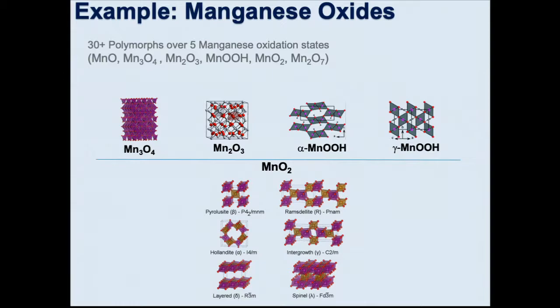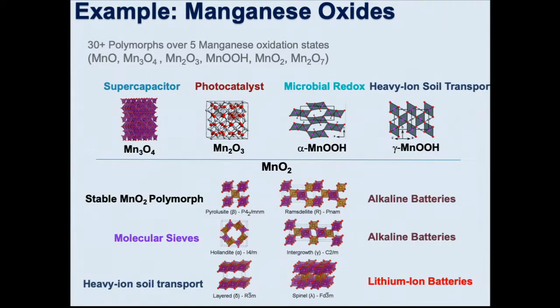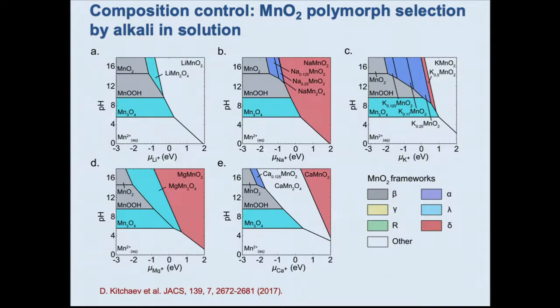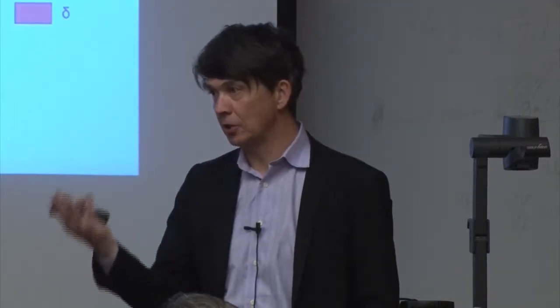So here's, I think, a simple one, the polymorphs of manganese oxide. So MnO2 has a ton of polymorphs, you know, pyrolusite, ramsdellite, hollandite, these kinds of tunnel structures. It has birnessite, a layered phase, it has spinels, roughly all the same composition, MnO2. So the question is, can you understand that stability? And you can, because they are often grown with alkalis in solution. And if you look at the phase diagrams of pH versus a chemical potential of an alkali in solution, you actually find that most of these phases, actually all of them, hollandite, birnessite, ramsdellite, appear somewhere on these phase diagrams. So the idea is that they are grown, or at least nucleated with the alkali, and then continue to grow and the alkali gets oxidized out.